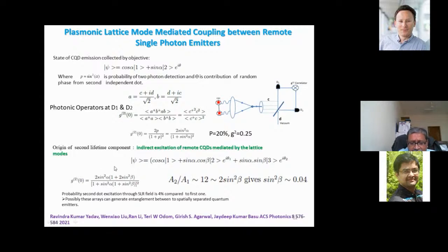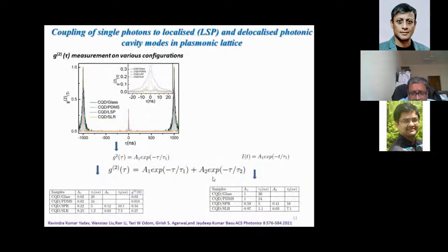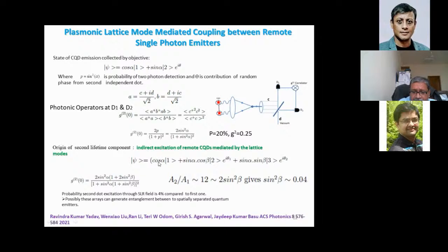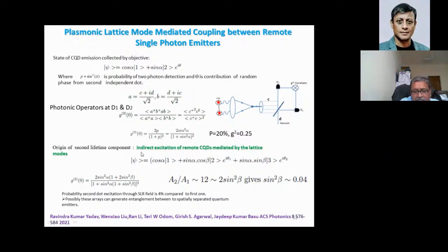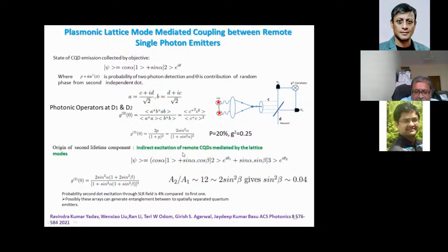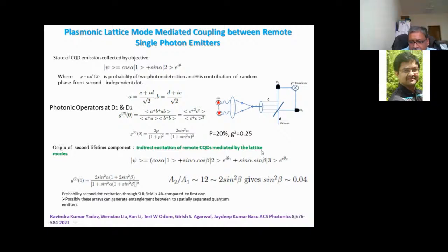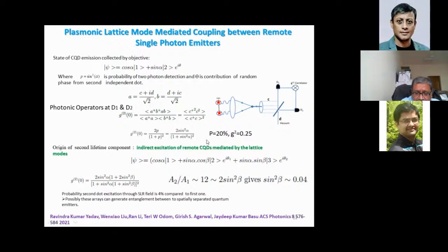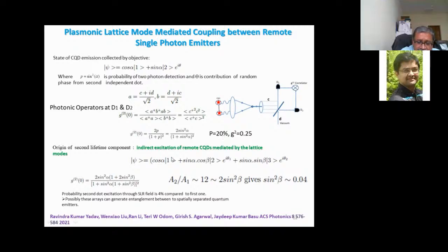But the other thing we try to look at is this second component that we see, as I mentioned here. It's there in both, but it's strong in the presence of the surface lattice resonance. So we feel it's because of the indirect excitation of remote quantum dots, which is mediated by this. The lattice resonance, as I mentioned, is delocalized, unlike the LSPR, which is strongly localized. That delocalized mode excites and de-excites, but it's sufficient to possibly excite indirectly another nearby quantum dot, and hence you see a very strong presence of a second kind of relaxation.